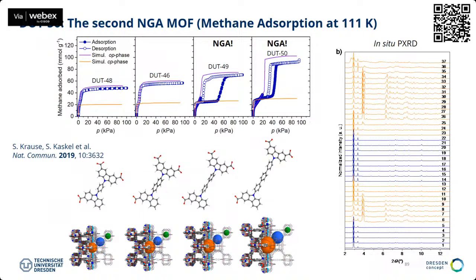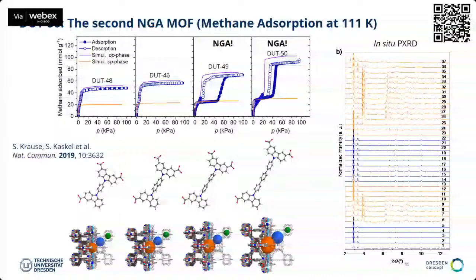When you look into the XRD, what you also see is the peaks of the contracted phase, but you still also see some peaks of the open pore phase. And I think these transformations become less distinct because the material in general becomes more flexible, more soft. So you also see a trend towards amorphization at a certain point. If your material becomes too soft overall, then you don't get a clear transformation between OP and CP form. But yes, this also buckles. It also shows the buckling.